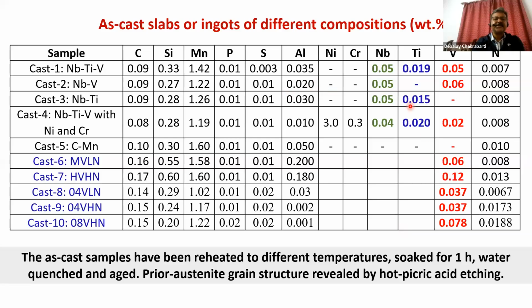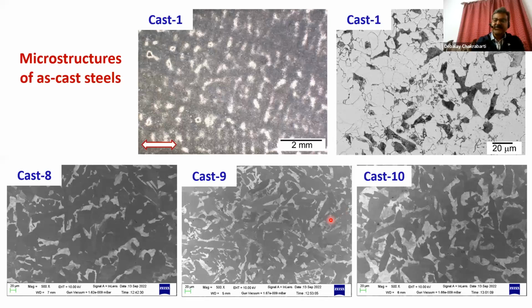So let me quickly go through what we have done in our study. We had some steels where we added niobium, titanium, and vanadium, all these elements, against some steels we melted only with vanadium with varying nitrogen and carbon content, just to compare how the niobium steels or titanium steels perform in comparison to vanadium steels. The as-cast structures were quite similar for all those steels.